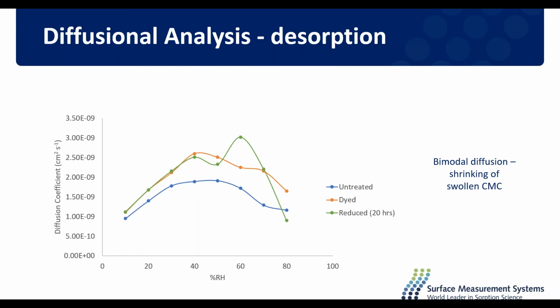And if we think about where these two stages are occurring from, the stage at about 40% relative humidity, similar to the untreated hair, is coming from the cortical cells, but these peaks that are appearing at higher relative humidities can be thought of if you consider the ability of the hair fibre to shrink and the diffusion pathways. As the hair fibre shrinks during desorption, the diffusion pathway for the water will also shrink. And that means that the diffusion for water can remain high. However, if you have a highly cross-linked sample, it's not going to be able to shrink, and therefore the diffusion pathways will remain longer, leading to slower diffusion.